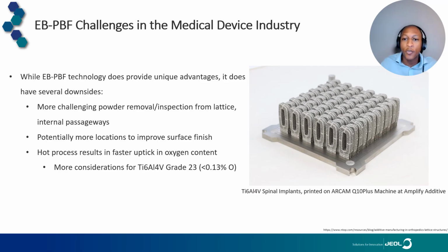That has to be considered when you are going from build to build, ensuring that your powder oxygen content does not go over the specification. In the case of, for example, Ti-64 grade 23, the oxygen content cannot be higher than 0.13.